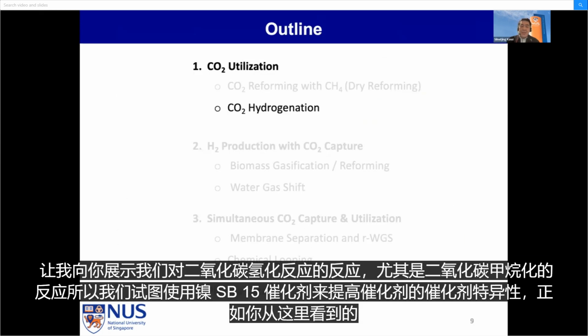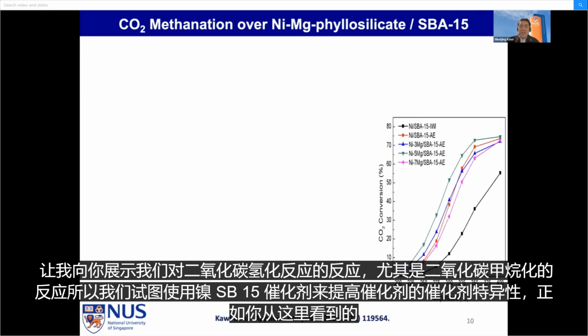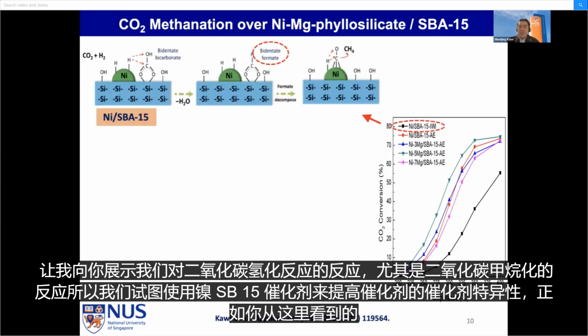Let me show you our reactions for the CO2 hydrogenation reaction, especially for CO2 methanation. We have tried to increase the selectivity of the catalyst using a nickel SBA-15 catalyst. As you can see from here, without magnesium, this is just a normal nickel SBA-15 catalyst. Bidentate formate is formed, but once we use magnesium, we form monodentate formate. And we have found that monodentate formate can be converted to methane much faster than bidentate formate. So that shows that medium-strength basicity can convert to methane much faster than strong basic sites.